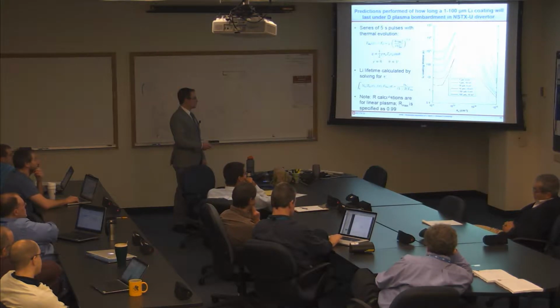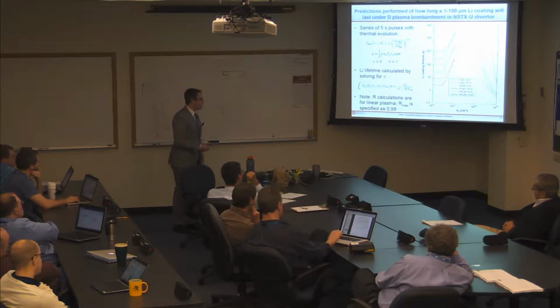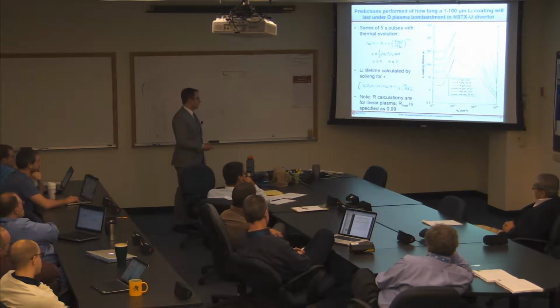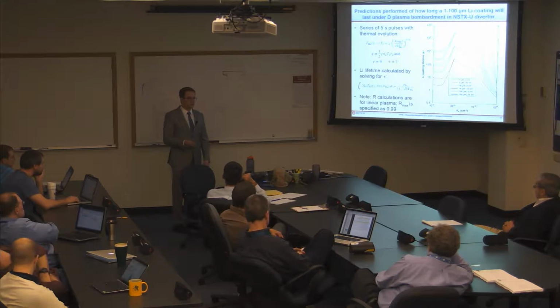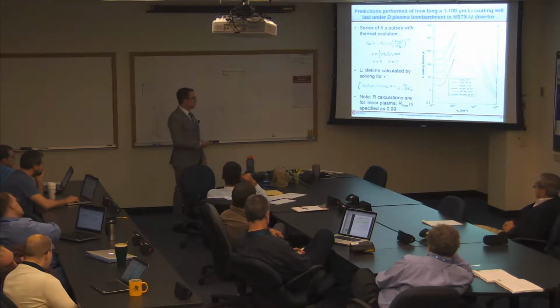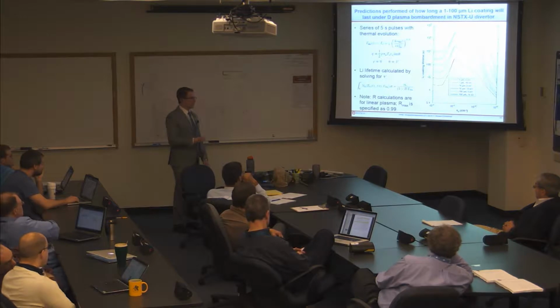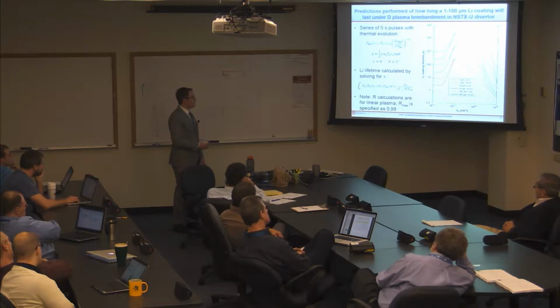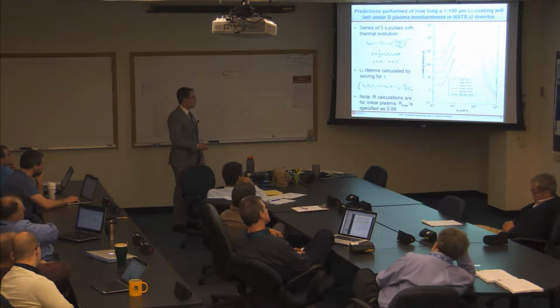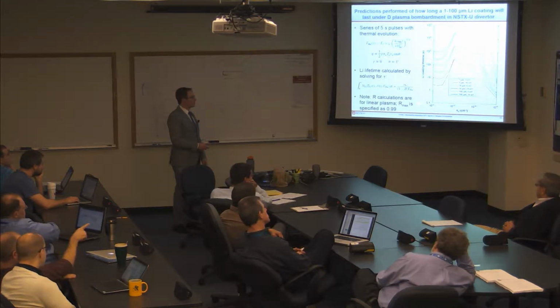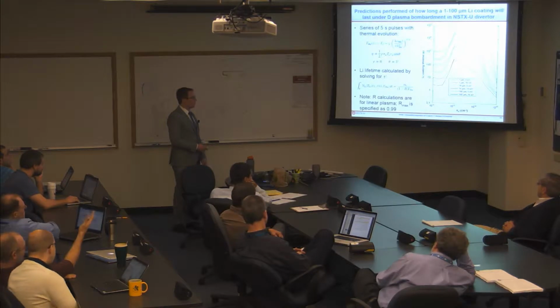And I should note that for the redeposition calculations, I assumed that the maximum redeposition fraction you could have is 0.99. The reason I did this is because you also have to worry about things like the transient startup and ramp down times of the plasma, where the density is a lot lower, and so the redeposition fraction is assumed to be a lot lower. Since I wasn't incorporating those into the model specifically, I just set a bound of 0.99 on the redeposition fraction.